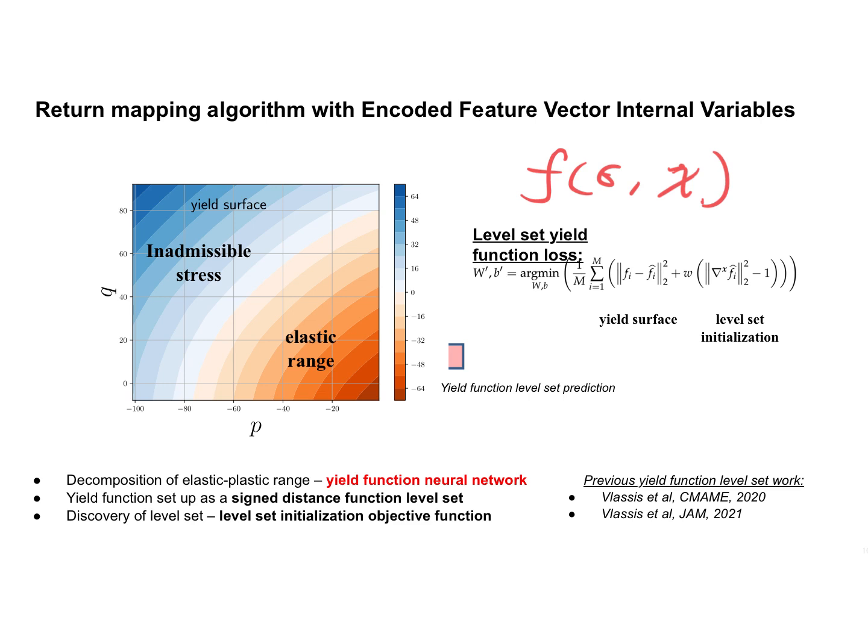Because if I'm changing it, I'm actually evolving the yield stress, and I know that is not perfect plasticity, right? Isotropic hardening and kinematic hardening are just two ad hoc examples that we add so that we can finish the model more easily. But in a more generic sense, it's just some kind of function that evolves over time, right? Does that make sense?